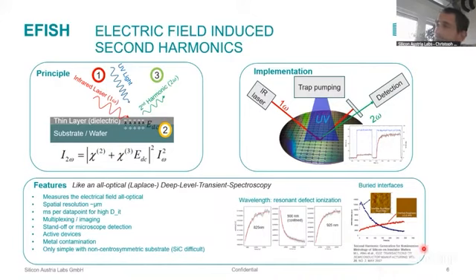This is also an interesting paper here on the right, lower right. It's not from us, but it has been demonstrated then that you can see even buried interfaces, buried oxide interface in this case. And here you have two examples, 10 angstrom RMS roughness and 3 angstrom RMS roughness, and you can see a dramatic difference in the signal. Of course, this atomic scale roughness is related to defects, and this is in the end what you sense with this. We also work more on the theoretical side.